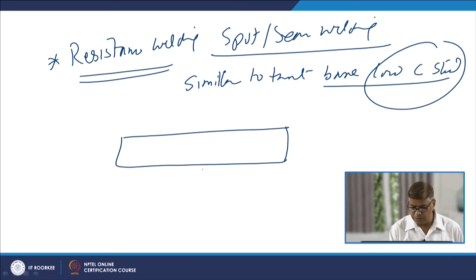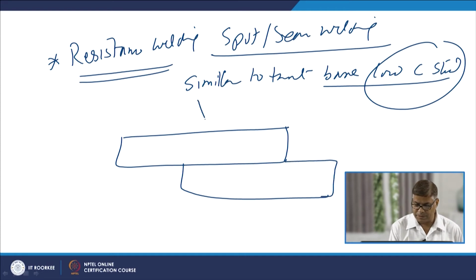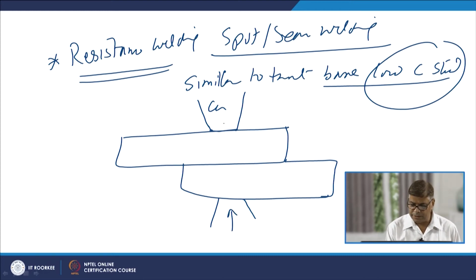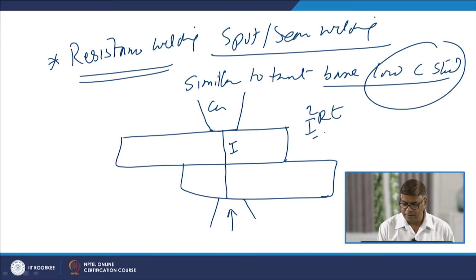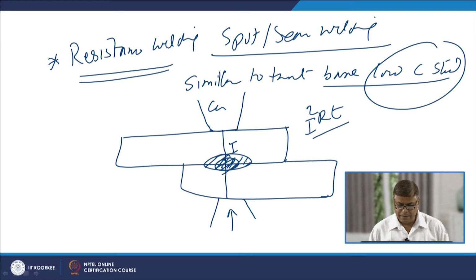To understand those issues, we need to understand a little bit about the resistance welding process. In the resistance welding process, the copper electrodes, which are water cooled, are brought in contact with the surface and used to apply the pressure, and once the sheets to be joined are in contact, the current is allowed to flow from one side to another. This current generates the heat by the I square R T principle. Since the contact resistance becomes the maximum in conventional resistance welding processes, maximum heat is generated at the interface, and that leads to the softening and the partial melting of the sheets to develop the nugget and ensure the metallurgical continuity between the parts to be joined by the resistance welding process.